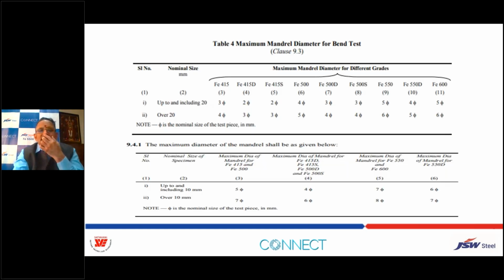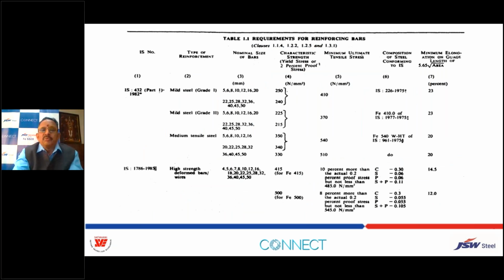So let us check the percentage elongation after testing of this and maximum mandrel diameter for the bend test, which I have shown before also. Even for HSD bars, we have to maintain this. And these are the characteristic strength and minimum ultimate UTS and composition of the steel as per the Codal provisions. This also I have shared before, mainly the carbon content, sulfur, and the phosphorus, and the combination of these two. We must test the steel not only for strength and percentage elongation. We should also test for these contents or get the manufacturer's report.